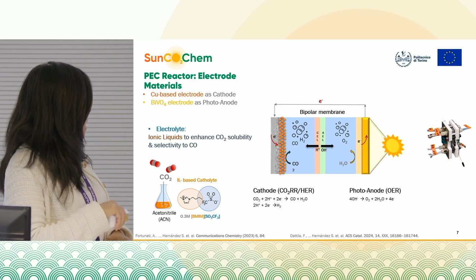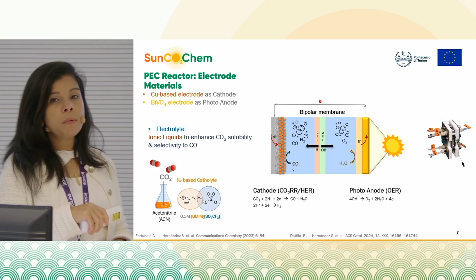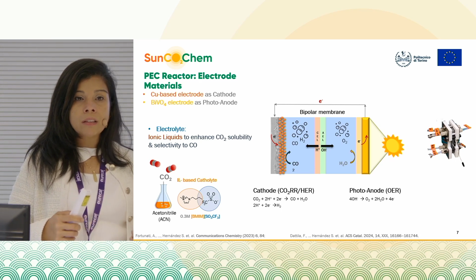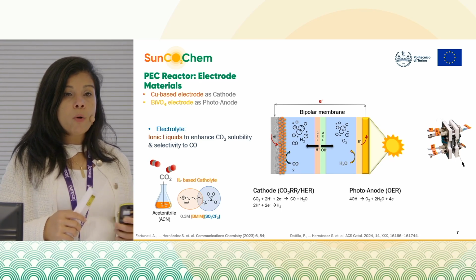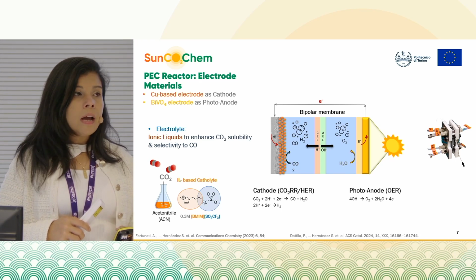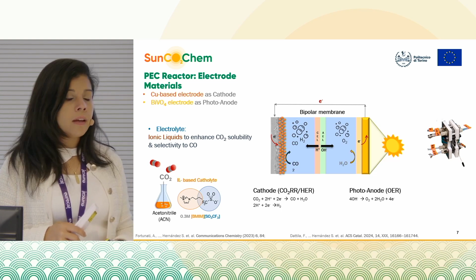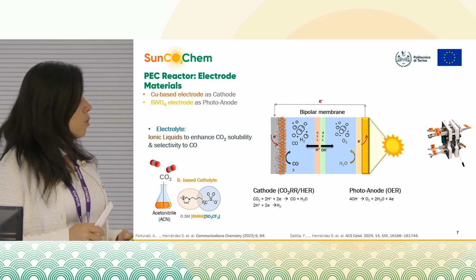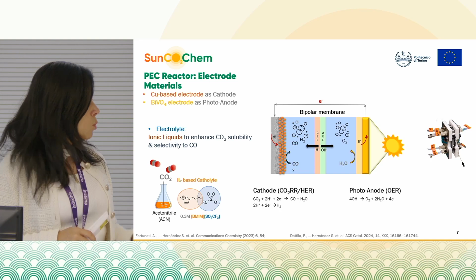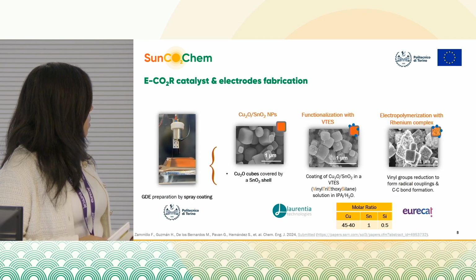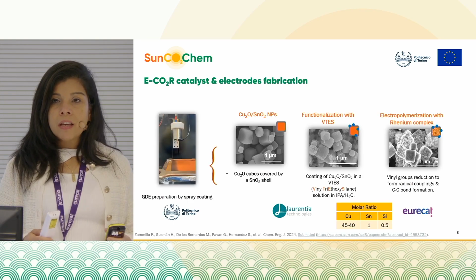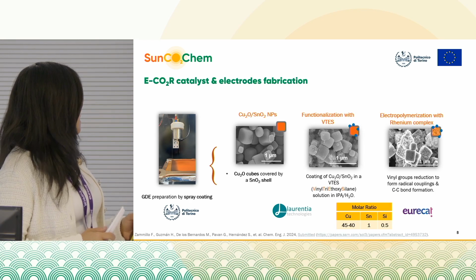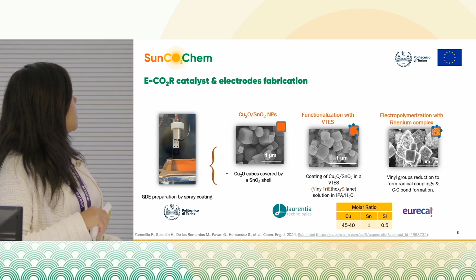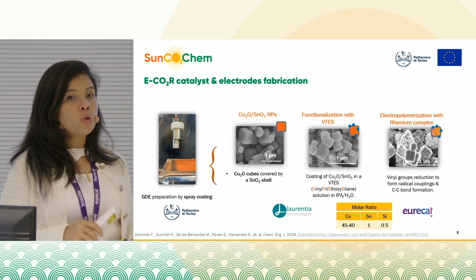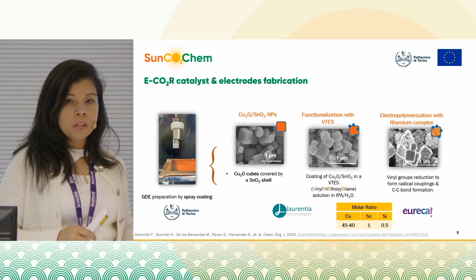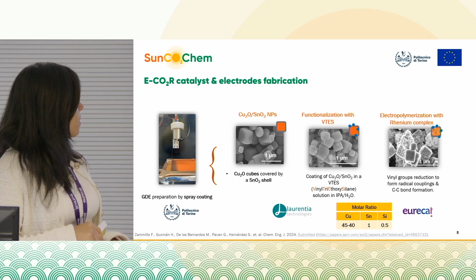In a first study, we identified that bmim triflate is a very good candidate of ionic liquid for promoting selectivity towards CO and co-catalyzing this reaction, other than having a good solubility of the CO2. And therefore, we started investigating that ionic liquid. At the same time, we developed a standardized and automatized procedure using spray coating for the preparation of the electrodes.